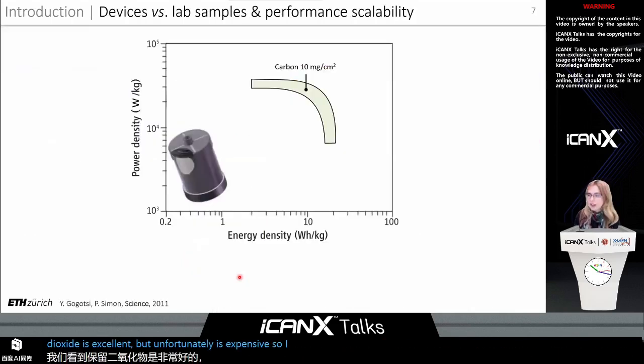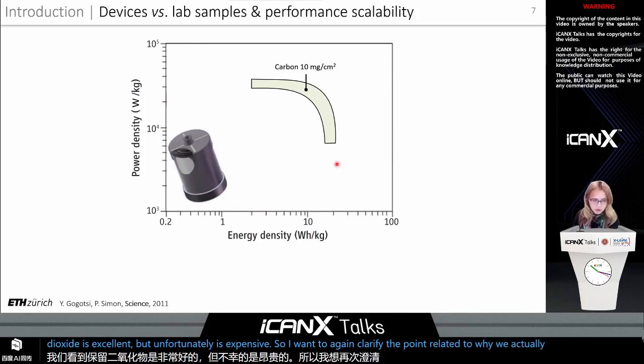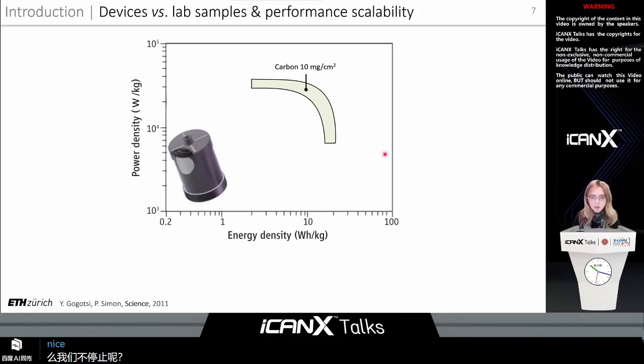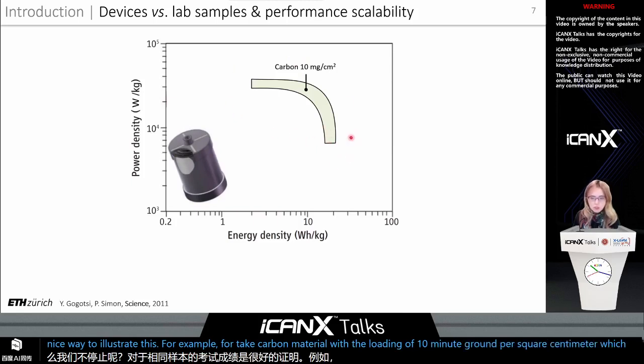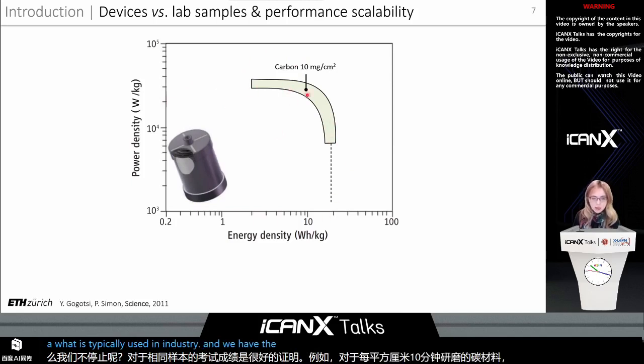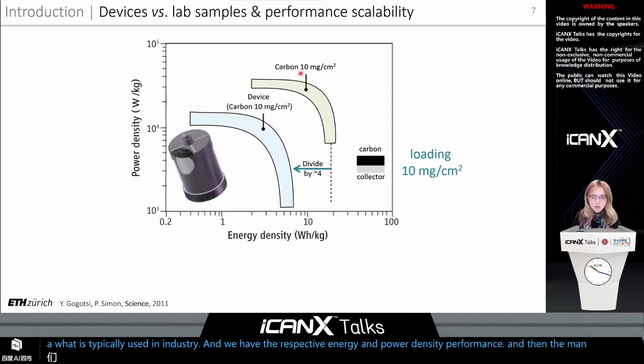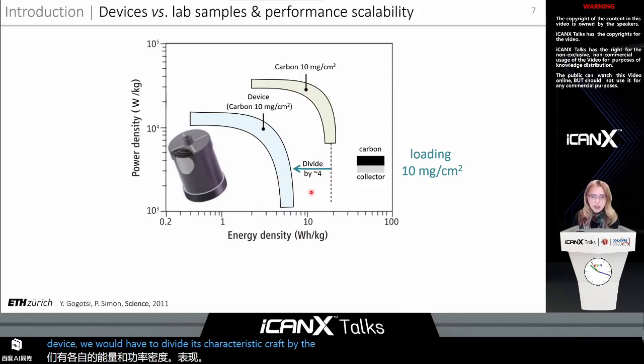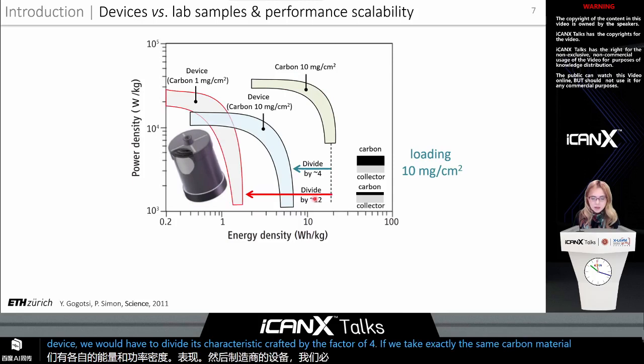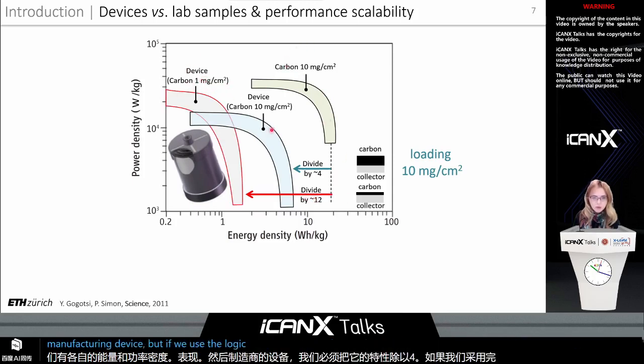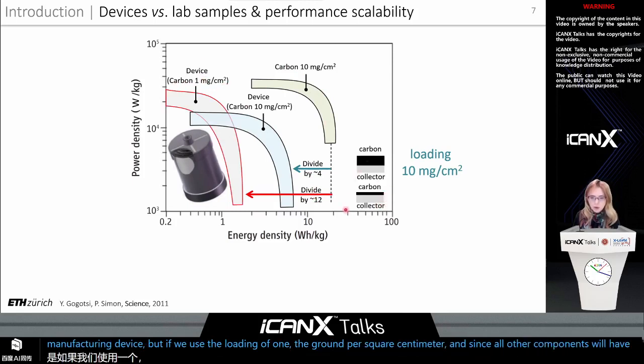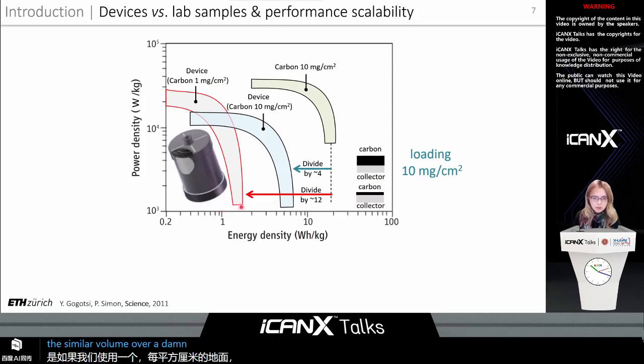So I now want to again clarify why we actually have to make sure that we can scale up performance for thick electrodes, and why we don't stop at excellent performance for thin samples. Here is a very nice way to illustrate this. For example, if we take carbon material with a loading of 10 milligrams per square centimeter, which is what is typically used in industry, and we have its respective energy and power density performance, and then we manufacture the device, we would have to divide its characteristics roughly by a factor of 4. Then if we take exactly the same carbon material and manufacture the device, but use a loading of 1 milligram per square centimeter, then since all other components will have a similar volume, the overall energy and power density of the device would be decreased by a factor of 12.